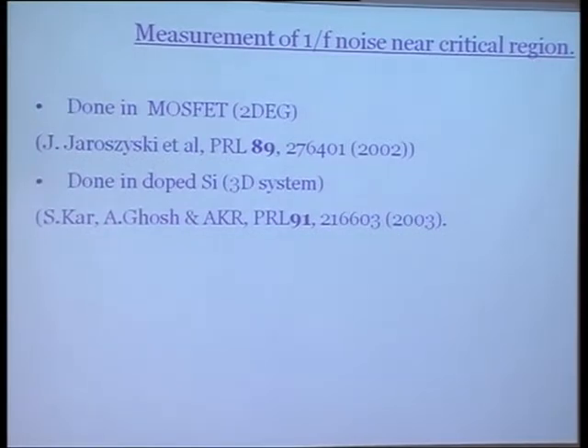So what do we see when you do a 1/f type of noise measurement near the critical region of that system? Unfortunately, there are not too many experiments. There's one reference I missed out over here that was published around the same time. In the 2D MOSFET, there was one paper which did find that the noise starts blowing out and becomes non-Gaussian, and there is a very good signature of slow relaxation. And this was the experiment Swastik Kar did for his thesis. He is now a faculty at Northeastern, and Arindam gave a beautiful talk just before me.